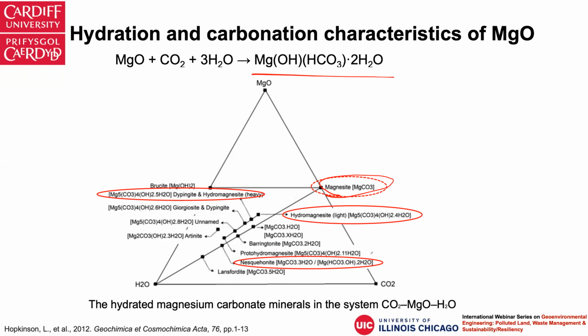These hydrated magnesium carbonates develop very high strength. Later you will see some images of these. They are either needles, flowers, or platelets with very small crystal size. So if you are using high concentrations of carbon dioxide under ambient temperature with humidity, you are producing a very dense microstructure that gives you very high strength.